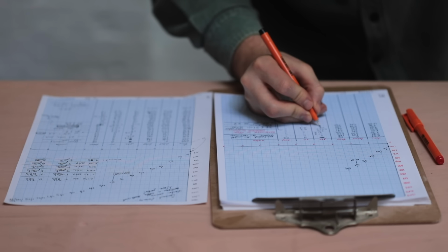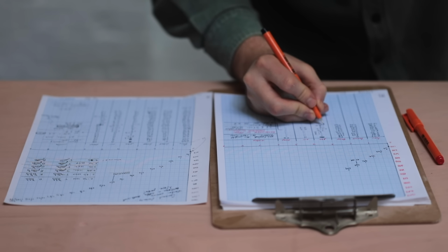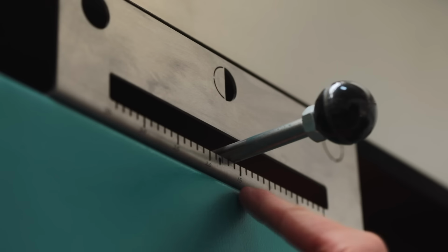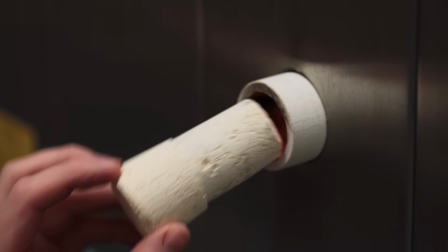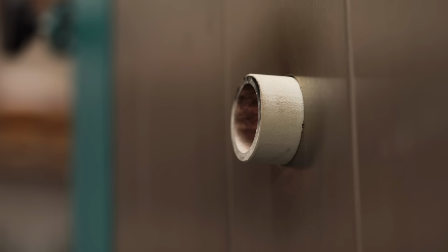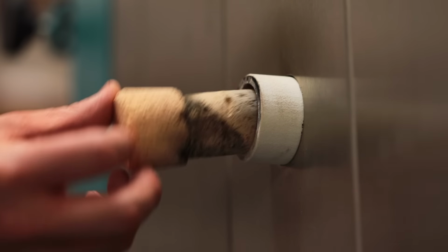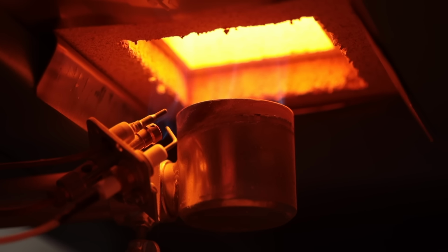Once the pyrometer reads 860 degrees, I initiate the reduction atmosphere by increasing the gas pressure, the air pressure, and by sliding the dampers to half cover the flues at the top. Simply put, this causes too much gas to accumulate inside with an insufficient amount of oxygen present for the fuel to burn efficiently. As a result, the burning gas seeks oxygen and finds it in the clay and glazes themselves, stripping it away and creating colours that you can only really achieve in a gas kiln. Once cone 10 is flat and the temperature reads roughly 1290 degrees Celsius, the kiln can be switched off.